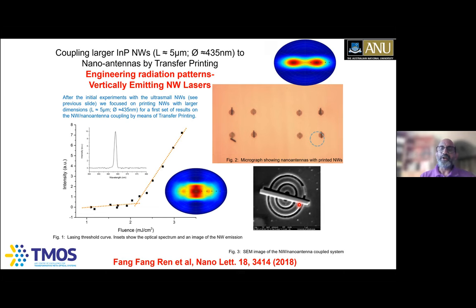If you do not have any nano antenna, light comes from both ends of the nanowire, as I showed you earlier, because the nanowire acts like a Fabry-Perot cavity. But when you have this nano antenna, suddenly light comes from the vertical direction, allowing us to make what is called a vertical emitting nanowire laser. Again, these operate at room temperature, and it created a lot of excitement in the community. You can see the threshold-like behavior.